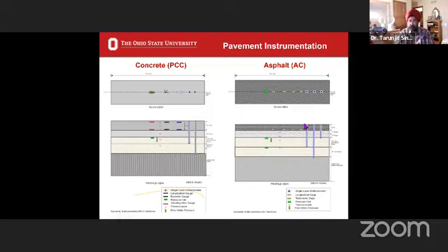And this then shows you a cross-section through the depth. This is the top view, and this is all under the wheel path. Then in asphalt pavements, we're also interested in the longitudinal and transverse strain at the bottom of the asphalt. So this is the asphalt layer, and this is the strain gauge, longitudinal and transverse. And as you know, in much of field work, if you're lucky, only about 80% of your instrumentation will work. About 20 to 30% will not. So you build in a lot of redundancies. You actually put more instrumentation in, knowing that about a third of the instrumentation will simply be garbage, or water will get there, or something will happen. And so we were looking at these locations.